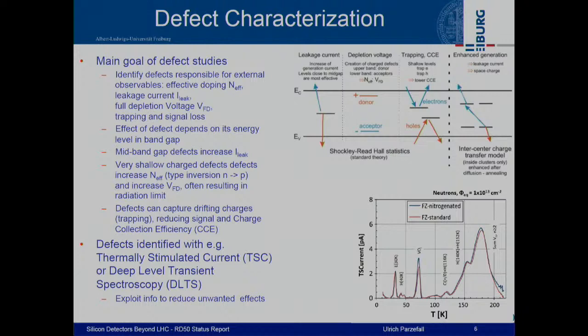More on defects: the main goal of defect studies is to identify the defects responsible for detector performance, for example looking at the effective doping concentration, the leakage current, and the full depletion voltage, which is directly linked to the doping concentration. You can see how different defects, based on their position in the band gap, affect the macroscopic properties we measure in different ways.